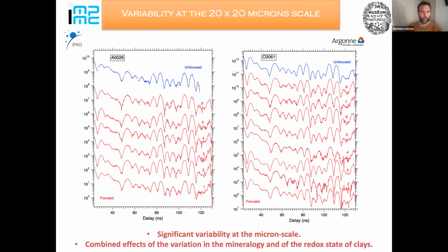We were able to look at the variability of the mineralogy at the local scale. So these are a series of NFS spectra collected on 2 large grains. And you can see that the mineralogy is pretty robust. You have some changes in terms of intensity, but all these spectra can be fitted just varying the amount of magnetite and clay minerals.